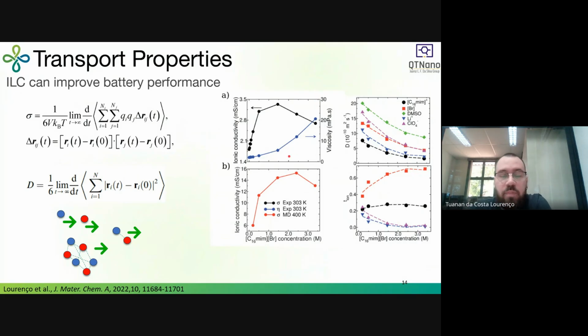And this was expected because ionic liquids are very viscous materials, so we are adding a viscous material inside a mixture, and it's expected that the viscosity is going to increase. However, if we think about Fick's law or any kind of transport law, we expect that if we increase the viscosity of a liquid, the mobility of the ions and the molecules is going to decrease. But if we look at the experimental data, what we see is an increase in the conductivity.